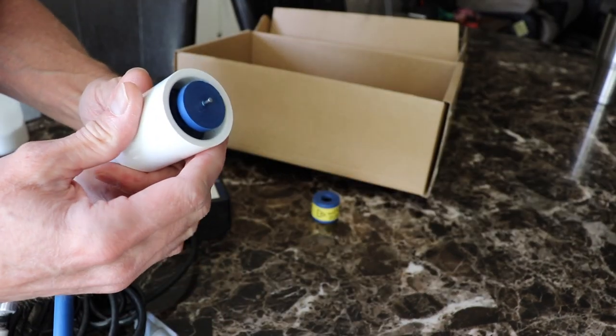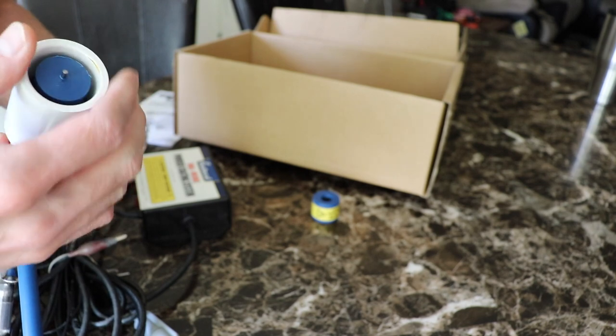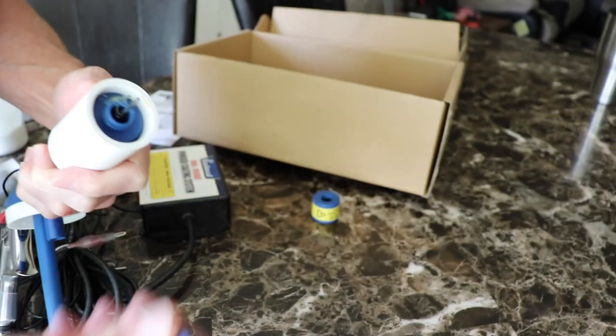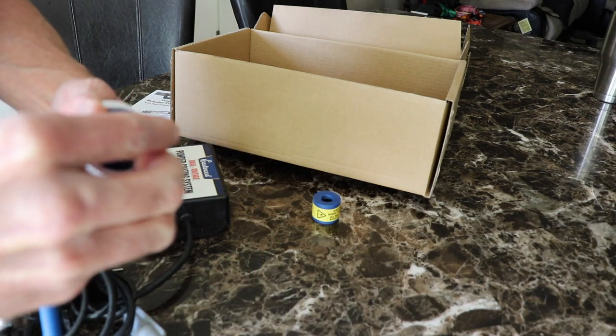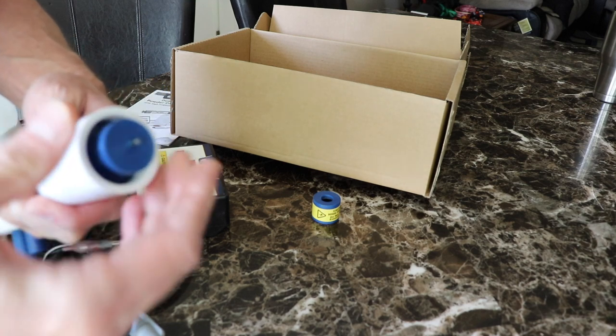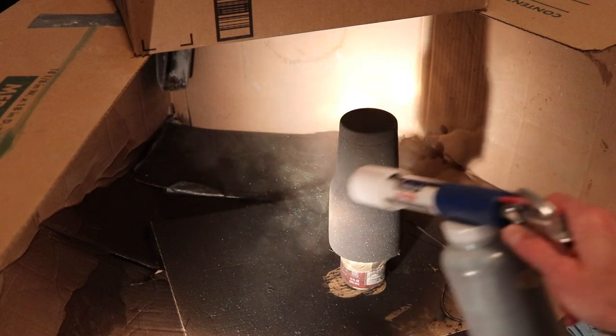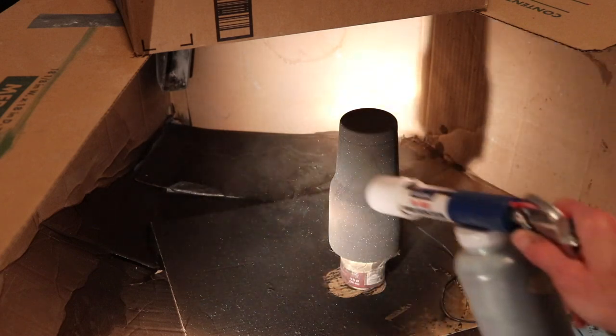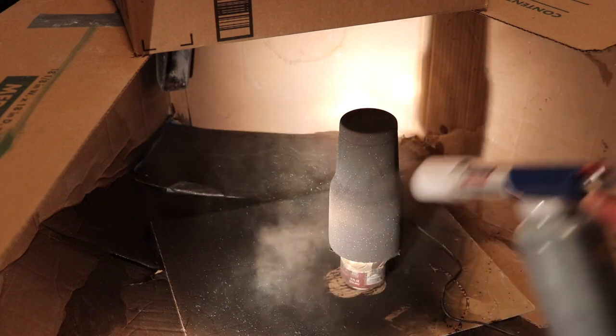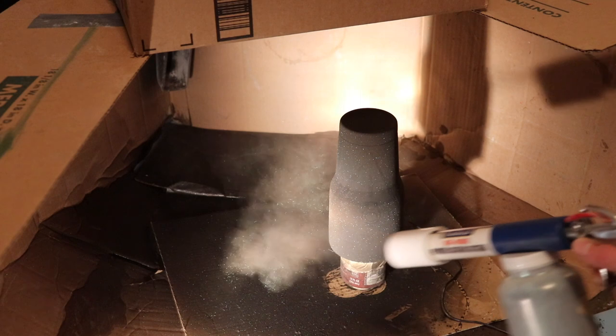And that's gonna give it more time to get a positive charge. And so that's gonna give you better adhesion onto your piece. So you can slow the powders down. Versus having just that off and straight shooting out, the powder's gonna be flowing too fast. You wanna keep it slowed, more slowed down. So that, you know, it doesn't just blow right past your piece. And you're not just wasting all this powder. Powder's not that cheap. So that'll help you focus in. Get a nice jet coming out of here that's not too fast.